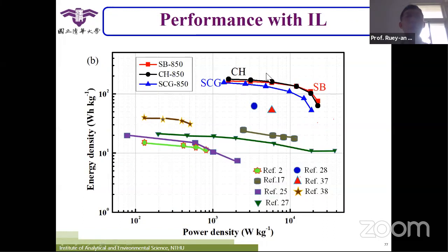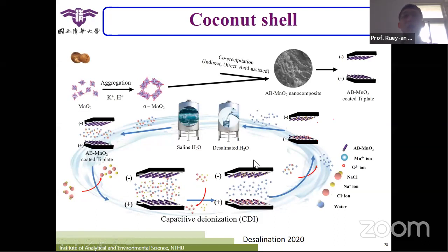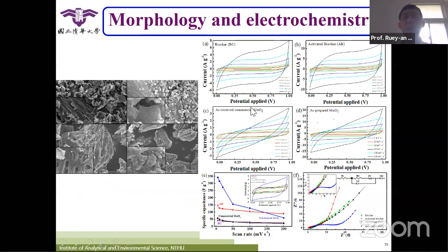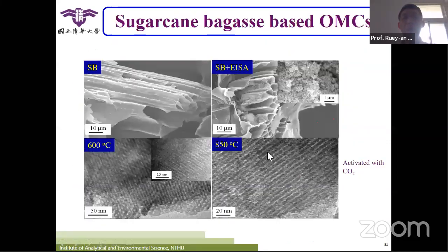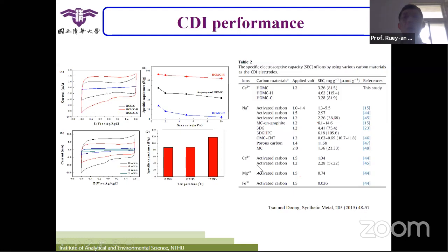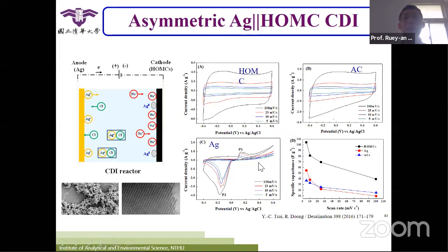Here you will always see we can go up to around 100, but unfortunately it is only around 30. So our goal is to try to move these ones to here, so that they can reach around 100 and 100. That is our goal. You can also use coconut shells to do it, and for CDI, we just published this in Desalination this year. You can also use the sugarcane bagasse as scaffolds to immobilize the highly ordered mesoporous carbon. All of these are possible.